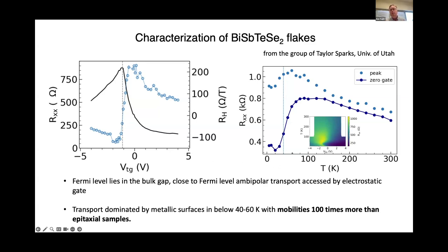If you measure the resistance as a function of temperature, if you gate them right near the Dirac point, the resistance goes up quite large, indicating that most of the bulk conductivity disappears below about 50 or 40 Kelvin or so. Near 0 gate voltage, you can see the contributions from the surface states as well, going down to low temperature. So those are the important starting materials.